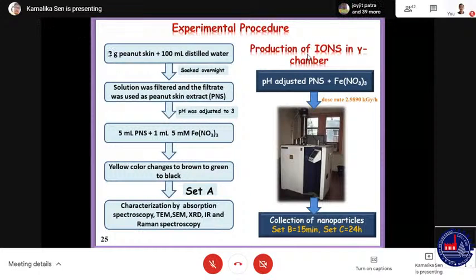So for that, we have taken 2 gram of peanut skin, taken in 100 ml distilled water, soaked overnight, and the red colored solution was filtered, and the filtrate was adjusted to pH 3, and to that we added 5 millimolar of ferric nitrate. The yellow color of the ferric nitrate then changes to brown, then to green, and then to black, indicating the formation of iron oxide nanoparticles, which we call set A, which is prepared without